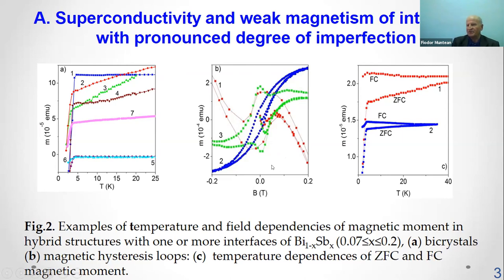Loops as those of type 2 superconductors, large crystallite disorientation angle bicrystal and more complex structure with a pronounced degree of imperfection exhibit superconductivity and ferromagnetism hysteresis loops. At the same time, a number of the bicrystals with a high content of imperfections and two superconducting transitions exhibit the dual superimposed ferromagnetic and superconducting loops, which indicates the simultaneously coexistence of superconductivity and weak ferromagnetism at interfaces.